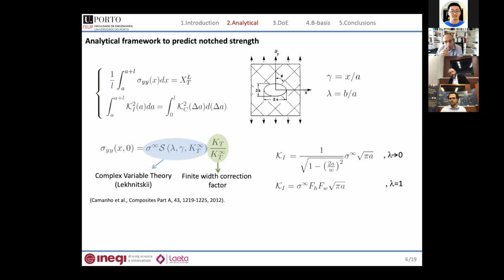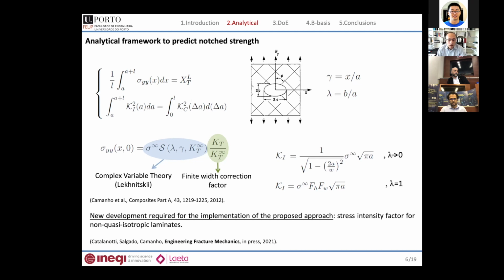Now, the thing that we have to keep in mind is that when we are using machine learning and we are sampling our design space, we may end up with non-quasi-isotropic laminates, and these solutions are only valid for quasi-isotropic laminates. So one additional step that we had to perform was to determine solutions for the stress intensity factor for non-quasi-isotropic laminates, and this was done recently in collaboration again with Giuseppe Catalanotti, and we have a paper that is in press that shows how we can obtain these solutions for the stress intensity factor for non-quasi-isotropic laminates.